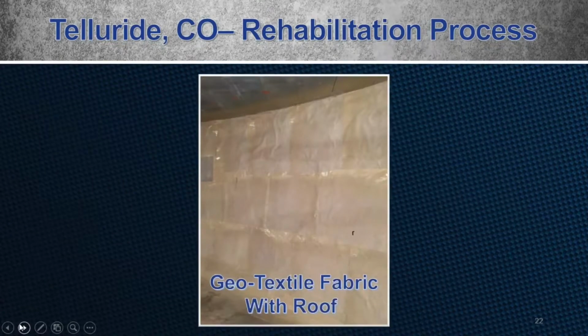Because of the drastic amount of movement that this structure saw over the past 90 years, we chose to use a geotextile fabric saturated into the first coat of polyurethane. What you're looking at in the picture is after the base coat was put on with the geo fabric inlaid. What that allowed for was, if there was drastic movement, you would have a separation in between the coats, and that geotextile would stay in place, adhering to the final top coat.